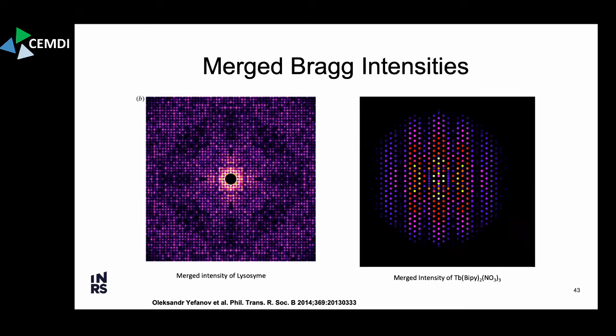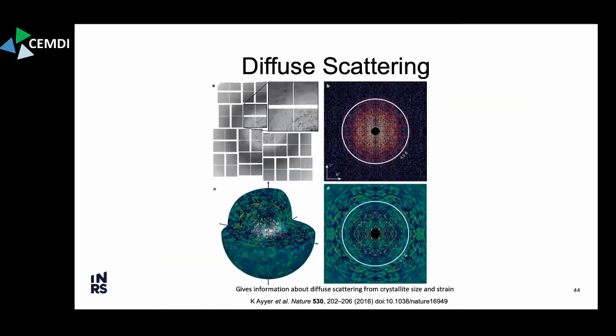And so what we have here is the HK0 plane, so cutting through the zero plane of reciprocal space for lysozyme. And here, this is the terbium bipyridine nitrate that we talked about in the beginning, merged up after doing the integration and merging. But you can go further, because you're throwing away a lot of information just by looking at the Bragg intensities. So you also have information around each reciprocal space point, which is this diffuse intensity.